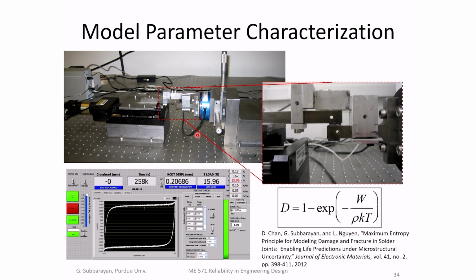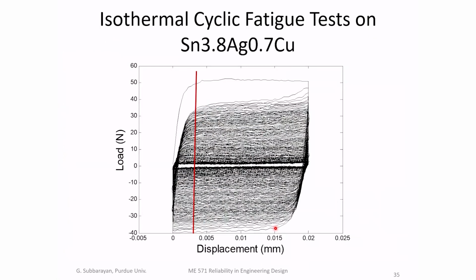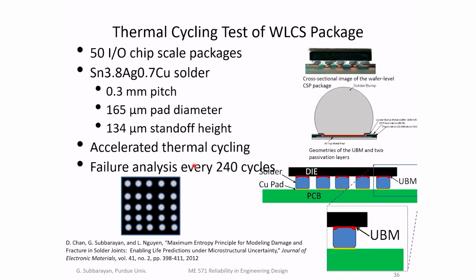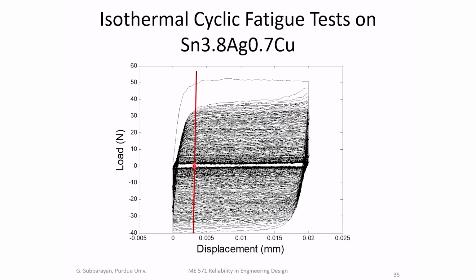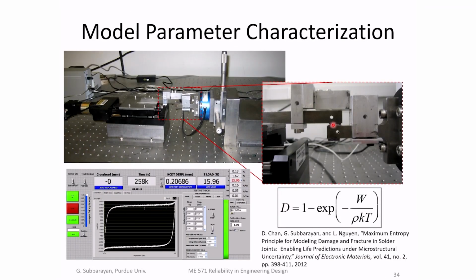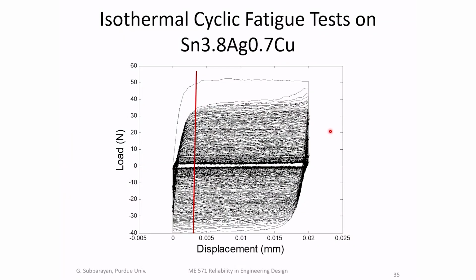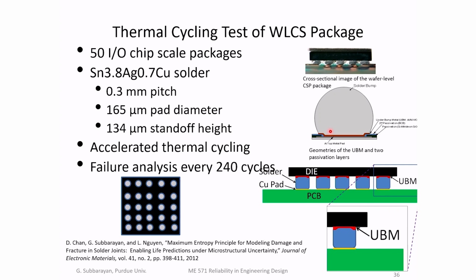This was a student's PhD thesis. So we would characterize the load drop from the first cycle to the last cycle, and then estimate that parameter K. Now we went and did independent thermal cycling experiments on a real package. So far, all the tests were done on a sample. The sample is different from a real package, and these were at isothermal conditions. So then we go do tests on a real package, and this package was from a company called National Semiconductor, which is now part of Texas Instruments.